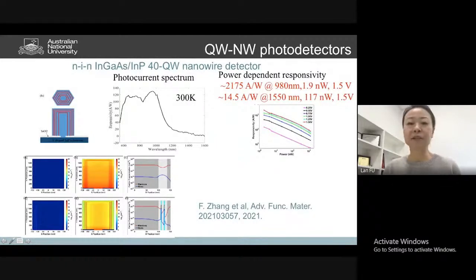So I'm running out of time. Basically, I just want to show that by incorporating quantum wells inside nanowires, you can also use them for photodetectors. Remember, when we put quantum wells inside, we achieve a different band gap compared to your host material, indium phosphide here, right? So by doing that, we can really extend the absorption and detection wavelengths to longer wavelengths, from around 950 nanometers for indium phosphide absorption all the way to 1.6 micron for indium gallium arsenide.